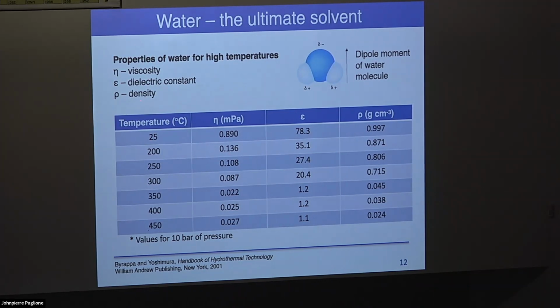You can see that at room temperature, it has a pretty high viscosity. Its dielectric constant is obviously pretty large, because it's polar, so it'll be used to help dissolve things that are polar. And its density is near unity, right? But as we start to increase the temperature, which is what you might do in hydrothermal synthesis, the viscosity goes down really low, which might be useful in crystal growth. The dielectric constant starts to approach unity. So at higher temperatures, you can start to dissolve things that might not be polar or might not dissolve in water at room temperature, and the density goes way down too.